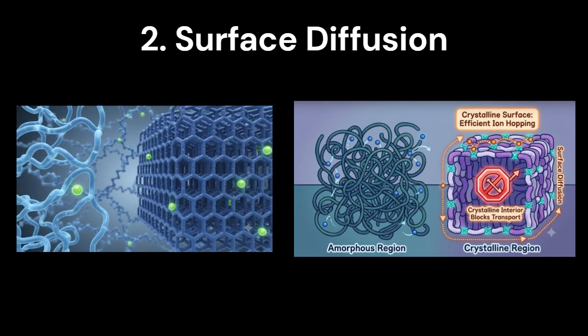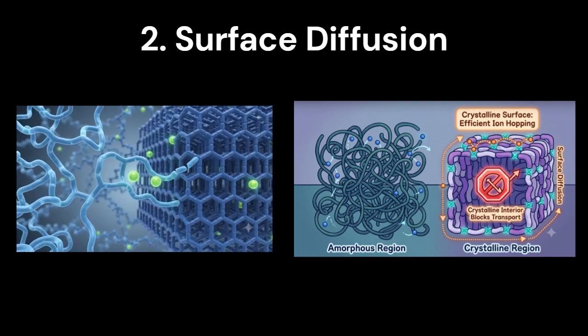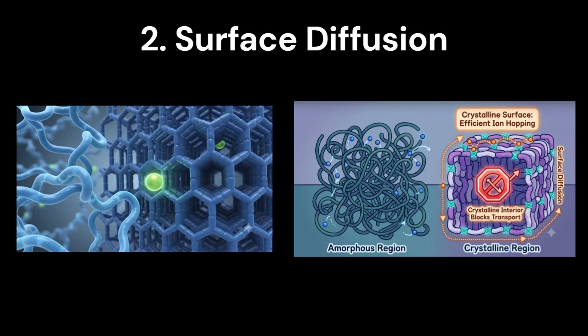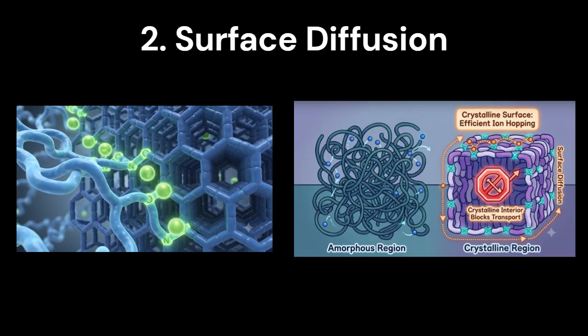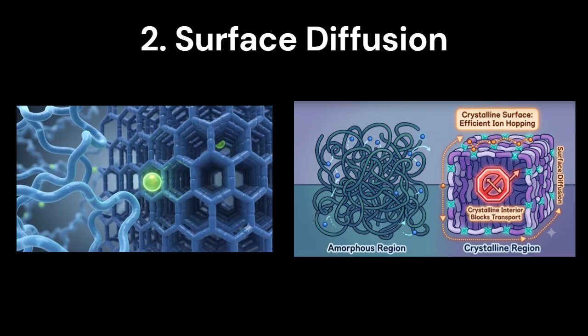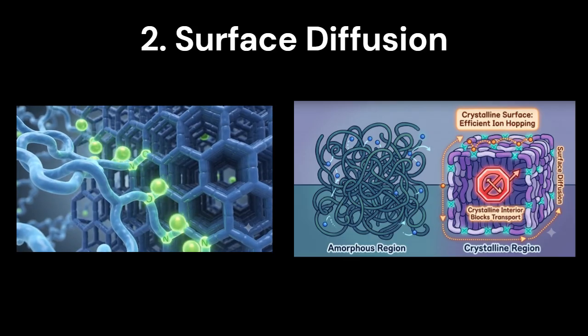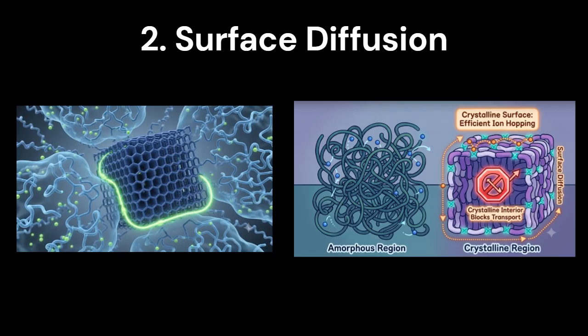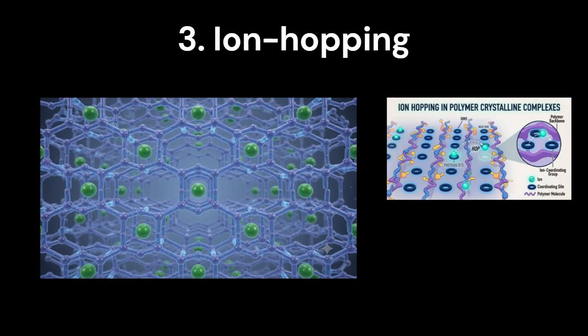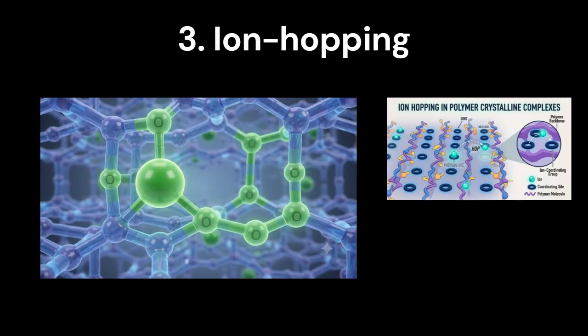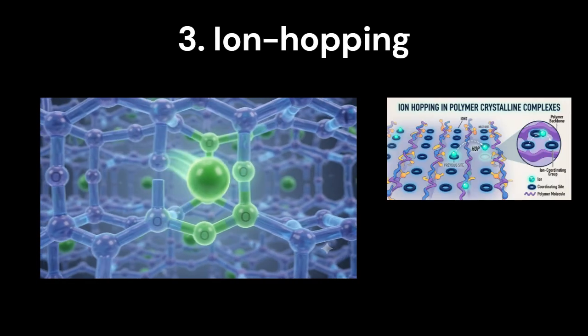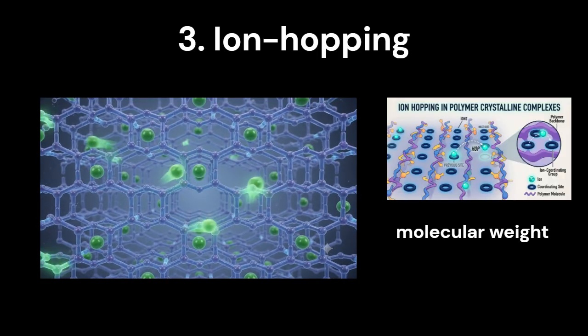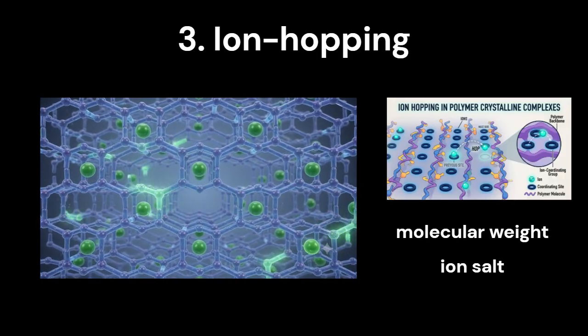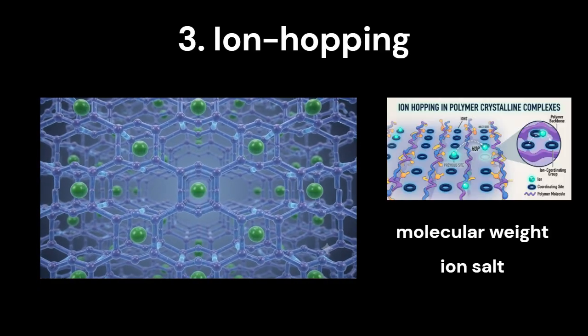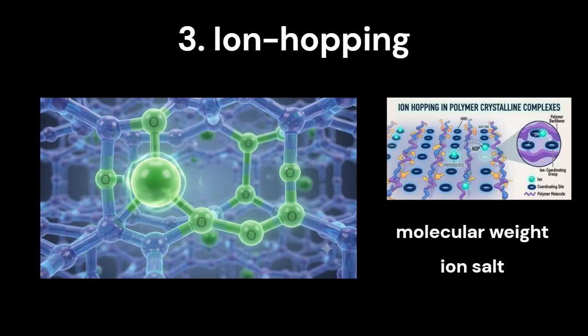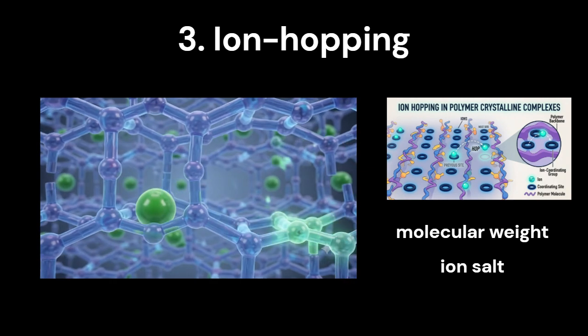Second, in mixed amorphous crystalline systems, ion transport can occur along the crystal surface through surface coordination, known as surface diffusion, while the intercrystalline regions hinder transport because the polymer segments are immobilized. Finally, in well-defined crystalline complexes, ions can move by hopping between adjacent sites. The molecular weight of the polymer and the type of lithium salt are therefore important factors, since ion hopping depends strongly on accessible defects in these crystalline polymers.